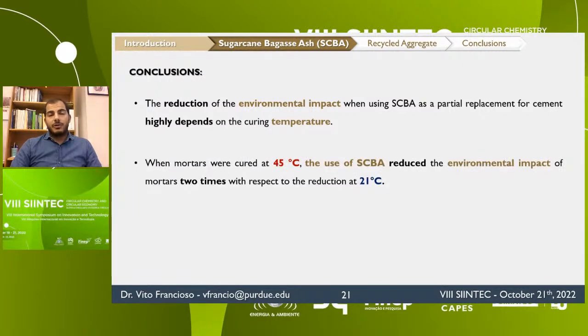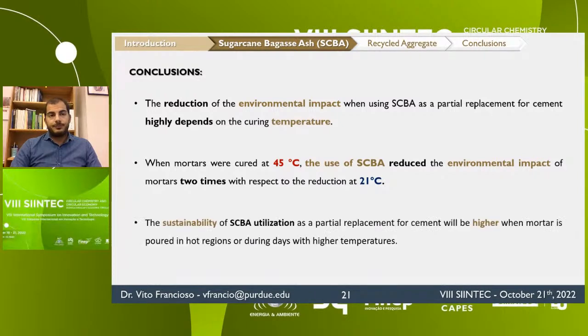When mortars were cured at 45 degrees Celsius, the use of sugarcane bagasse ash reduced the environmental impact of mortars 2 times with respect to the reduction at 21 degrees Celsius. And then the sustainability of sugarcane bagasse ash utilization as a partial replacement of cement will be higher when the mortar is poured in a hot region or during days with higher temperature. Therefore, the external curing temperature is an important factor that should be considered when the sustainability of cementitious composites containing sugarcane bagasse ash, but also other biomass ashes, is assessed.